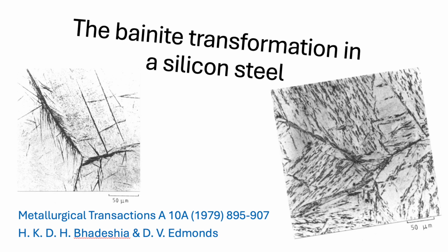Wow. Okay, twinning is one piece. What was the second? The second came from how the carbides precipitated. As we said, they formed inside the laths. Critically, they weren't observed at the very, very earliest time, suggesting precipitation happened after the ferrite formed. Right. And when they did appear, they often precipitated on more than one variant of their crystallographic habit plane within the same single ferrite crystal. Multiple orientations of carbide plates within one ferrite grain. What does that tell us?